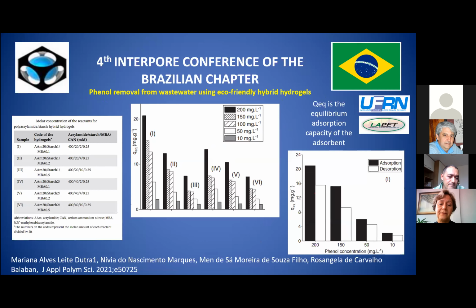The same hybrid hydrogels we applied to evaluate the removal of phenol. So we evaluated all the hydrogels, and you observed that depending on the composition of the hydrogels, we can have different behaviors with different capacities of adsorption. The best results were obtained for the first sample with the lower concentration of cross-linker and starch.